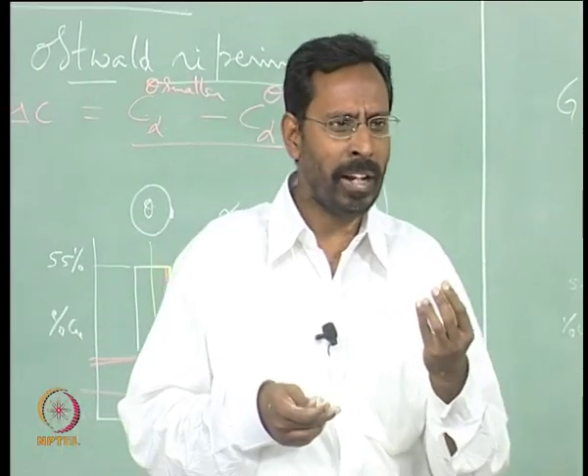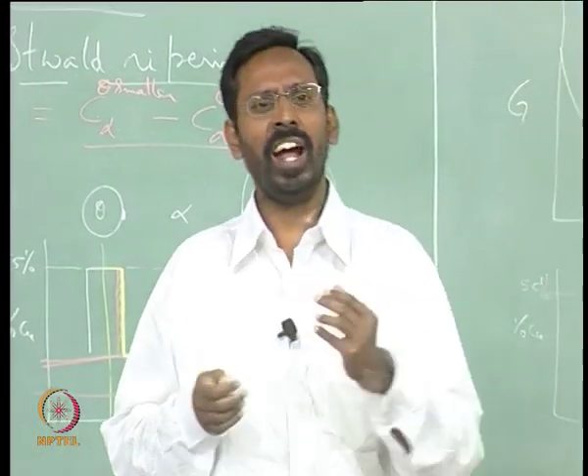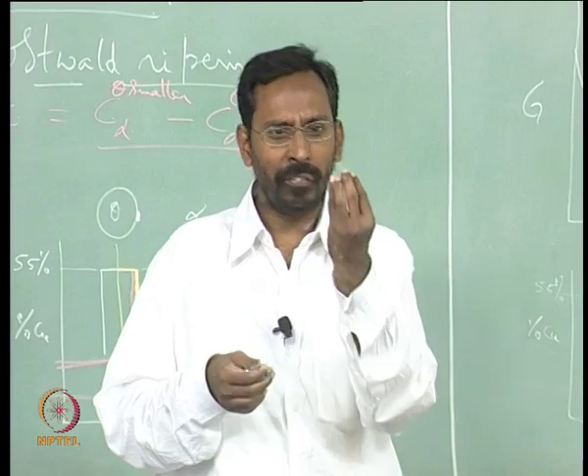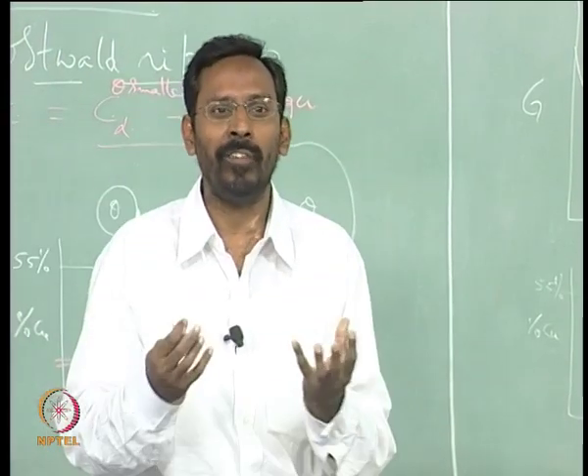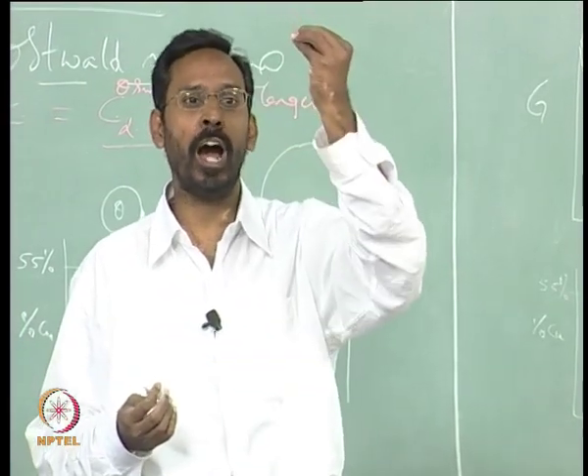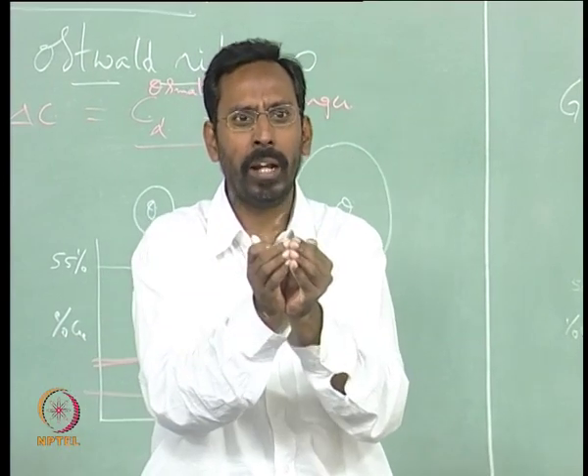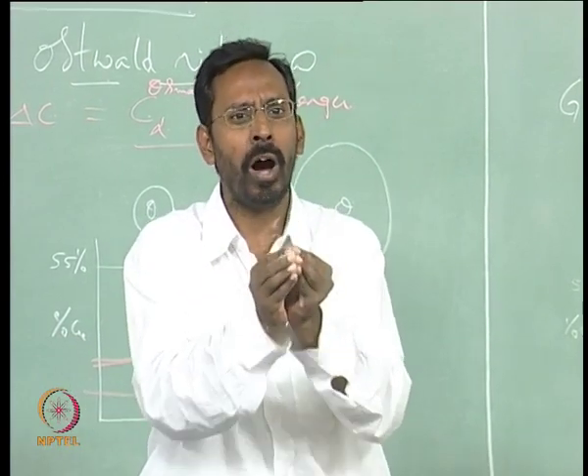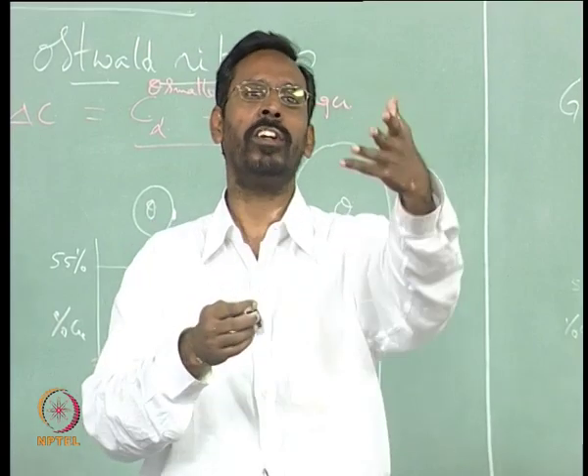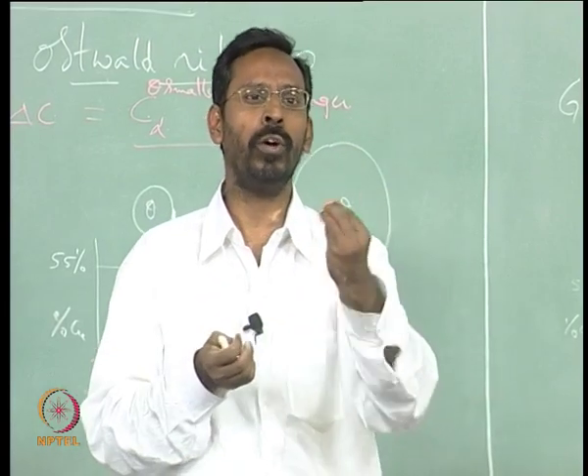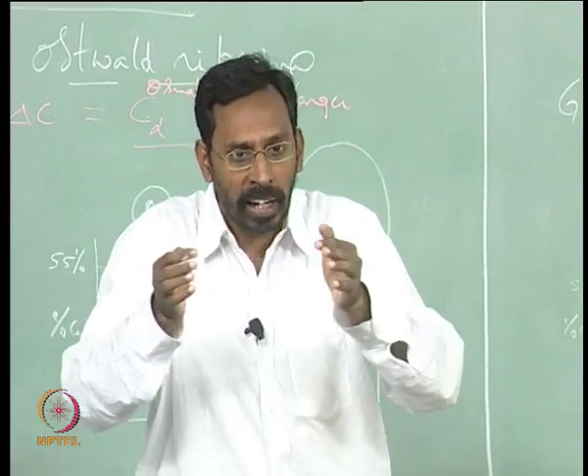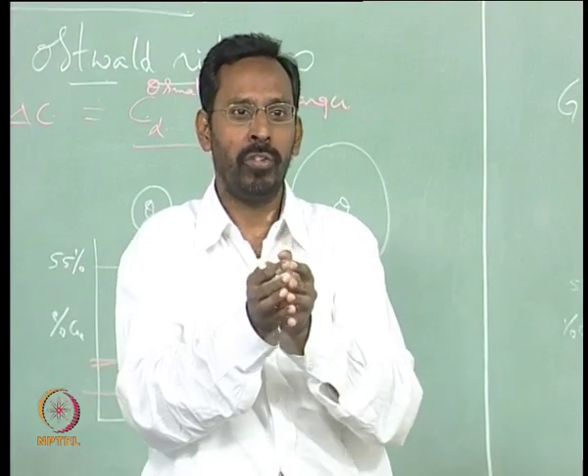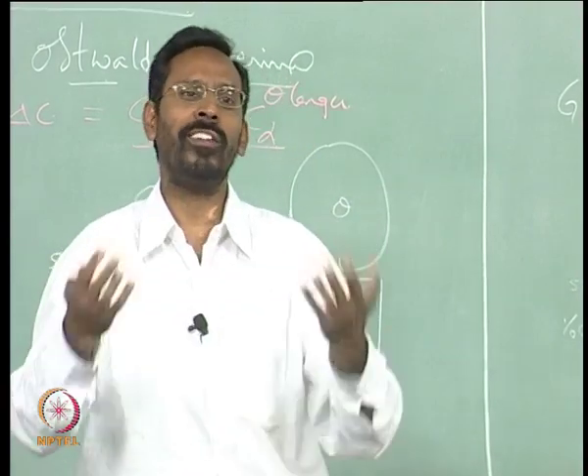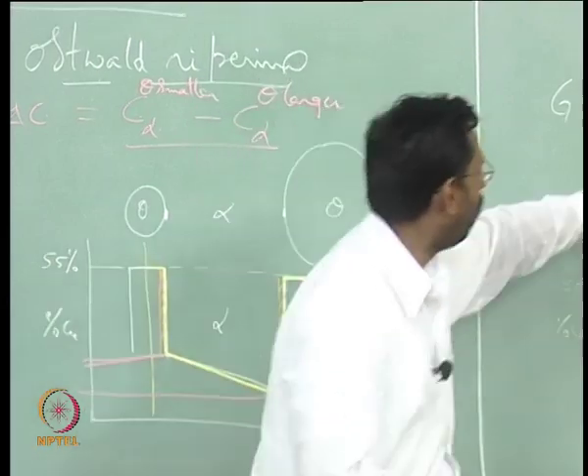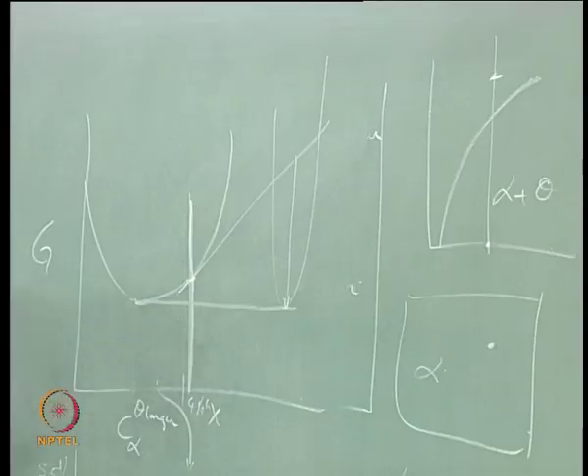In fact, this can even be physically understood. When you think of a theta nucleating inside an alpha, theta having a higher copper content, copper atoms get accumulated in a small region, and that region gets converted to theta. If you want to call it a nucleation event, they are getting accumulated from alpha. So, the region adjacent to that is obviously depleted, and this depleted region has a different composition.